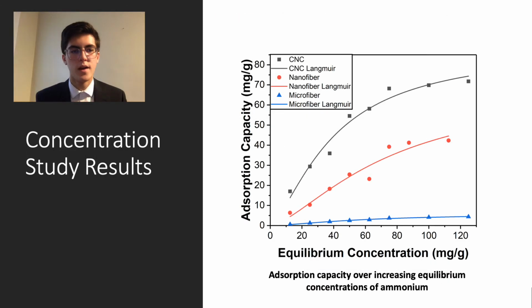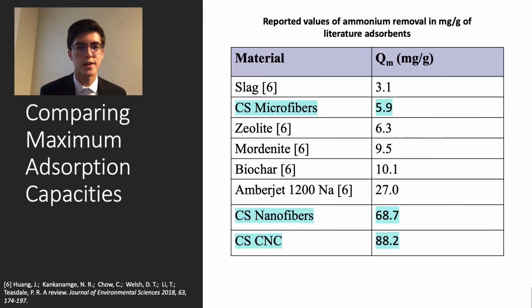The concentration study indicates that ammonium removal increases with increasing equilibrium ammonium concentration, with the maximum absorption capacity from the Langmuir isotherm achieving 88.22 milligrams per gram for nanocrystals, 68.71 milligrams per gram for nanofibers, and 5.97 milligrams per gram for microfibers. By comparing the maximum absorption capacities of my materials to materials that are listed in literature, it can be noted that my materials are all competitive with materials that exist in the literature, with the nanofibers and nanocrystals being particularly competitive. But even the nanofibers, which technically is the reaction that involves the less application of acid and no energy cost because of homogenization, are still competitive with things like slag.